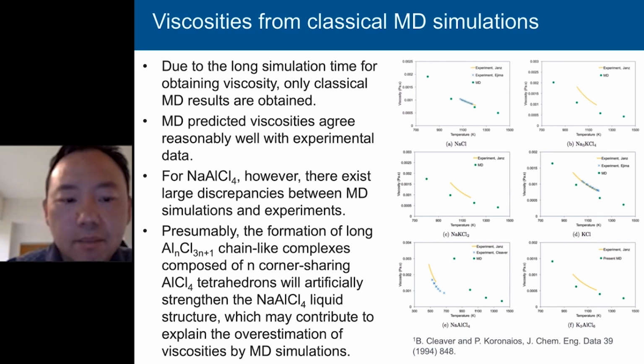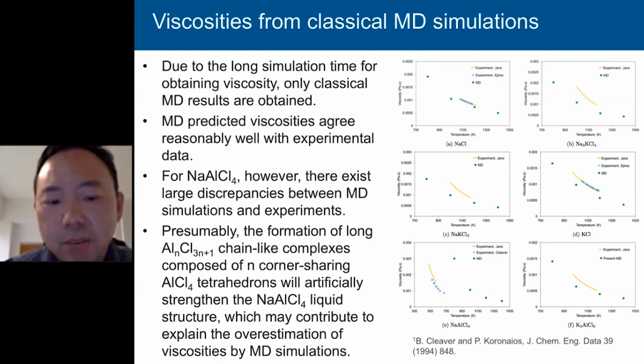As I mentioned before, the classical MD simulations form very long aluminum chloride chain-like complexes, which are composed of corner-sharing aluminum chloride tetrahedrals. These chains can artificially strengthen the liquid structure, therefore giving a high viscosity, which I believe is the origin of this discrepancy between modeling and experiments. So this is the only case where the error is large. For the other chemistries, the agreement is very, very good.